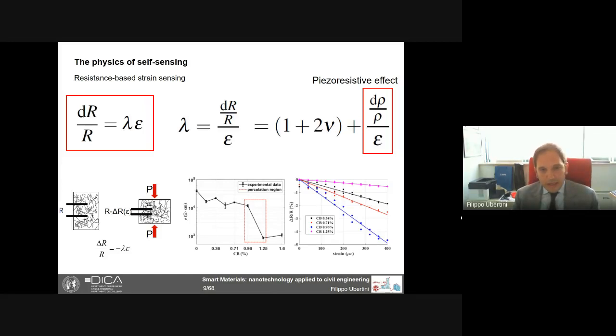It can be shown by the theory that the gauge factor is maximized for a specific content of nano inclusions that depends on the shape and the properties of the nano inclusions. That's called the percolation threshold. What's the percolation threshold? It is essentially the critical fraction of nano inclusions that makes the electrical conductivity jump dramatically from the value of the matrix up to the value of the composite. Let's say the material passes from being an insulator to being a conductor.